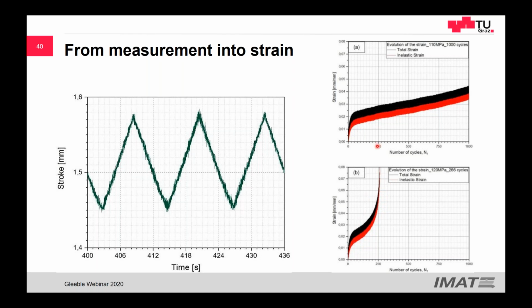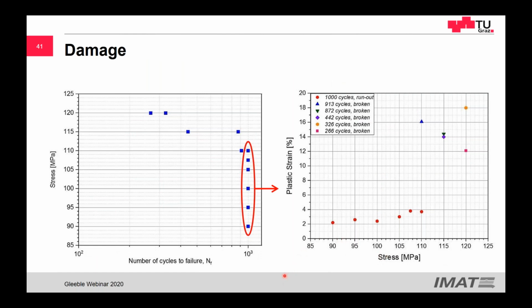As we can see here, the curve looks a bit like a creep curve, but all this, what you see here in red, you have to imagine had the shape of a triangle, going up and down with temperature. We got this inelastic strain as a function of number of cycles. And of course, the higher the stresses, the lower the number of cycles. You reach some kind of tertiary creep. And then we measured the number of cycles to failure as a function of the stresses. So you can see the higher the stresses, the lower the number of cycles the material resists.